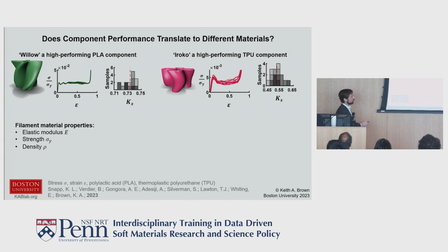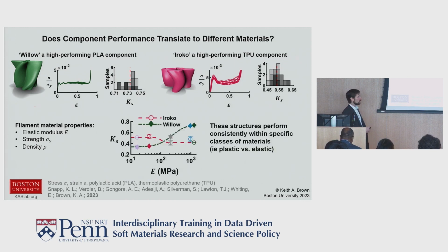We can compare this to what we call Iroko, a part first discovered in a thermoplastic polyurethane material. It tends to have a little under 55% efficiency. It turns out that the more elastic materials, thermoplastic elastomer being a more hyperelastic material, aren't as efficient, for reasons that come from the mechanics. So we could ask, does a part that's good in TPU look good in PLA, and vice versa? Here are the results of that.